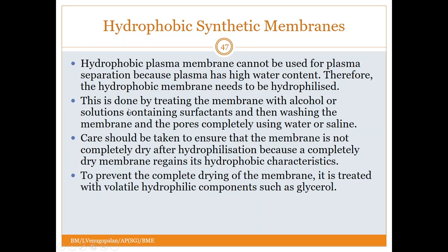You have to make sure that the membrane has affinity towards water. That's when it would invite plasma to pass through it, and that can be done by either treating the membrane surface with alcohol or solutions that contain surfactants, and then washing the membrane and the pores completely with water and saline. So you have to make sure that the membrane is not totally dry after washing this out.